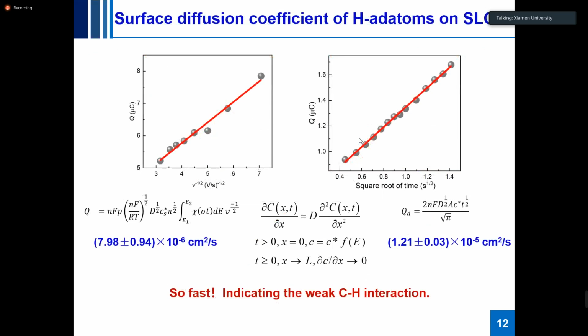From the linear relationship between the integral charge and the square root of the scanning rate, and also the square root of the time, we can figure out the diffusion coefficient of the surface diffusion of hydrogen atoms on the graphene. We can see that it's so fast, on the order of 10 to the minus 5 square centimeter per second. This is a very fast diffusion coefficient, also indicating the weak interaction between the carbon and the hydrogen atoms.